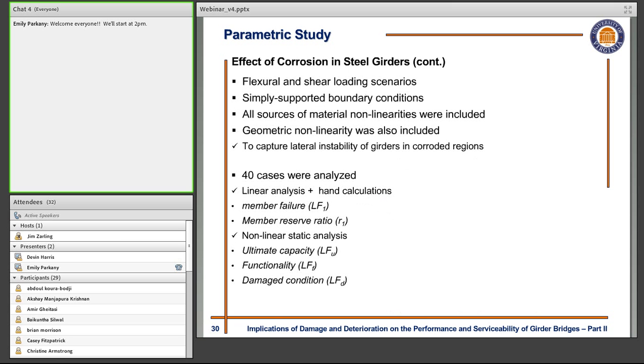Regarding the analysis, we performed the same type of analysis regarding boundary condition. We applied simple supported boundary condition for both of these structures, as they're reported in their as-built plans and also design plans. Regarding the loading configuration, we considered flexural loading and shear loading scenarios, where we put the truck loading at the middle span of the structure and also close to the supports.